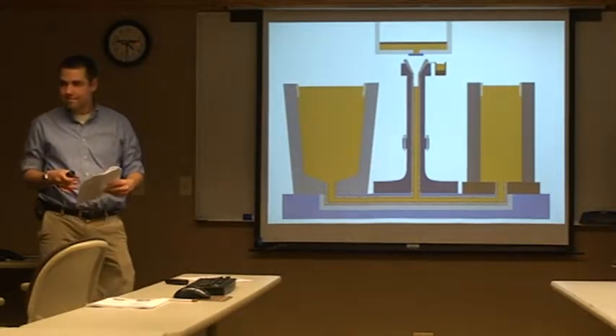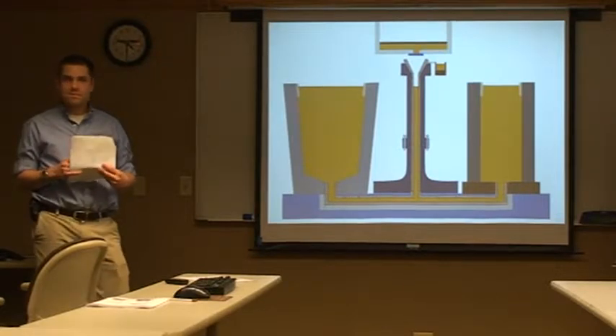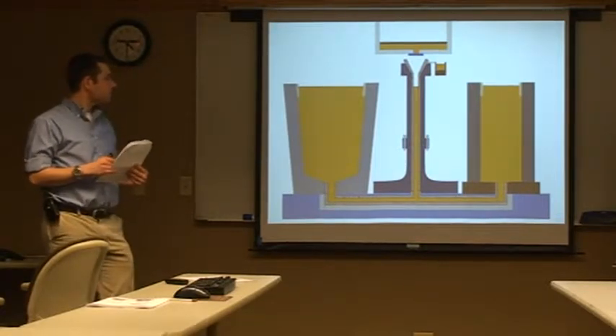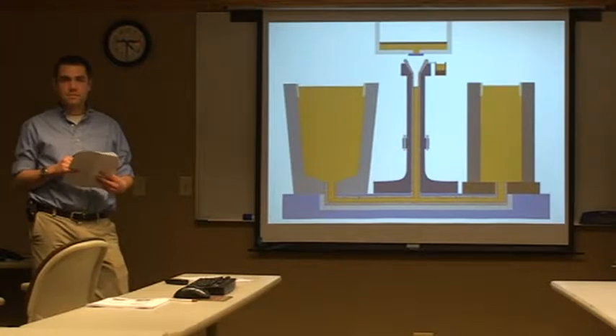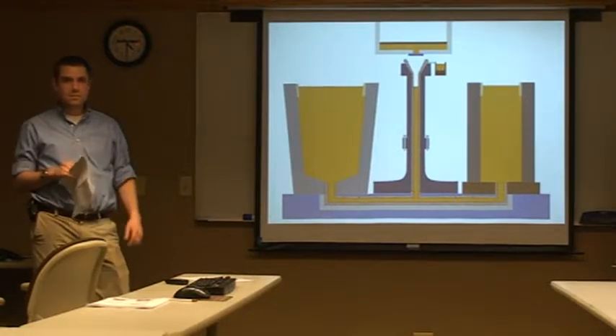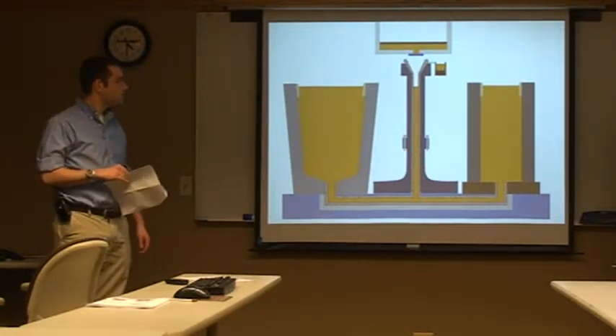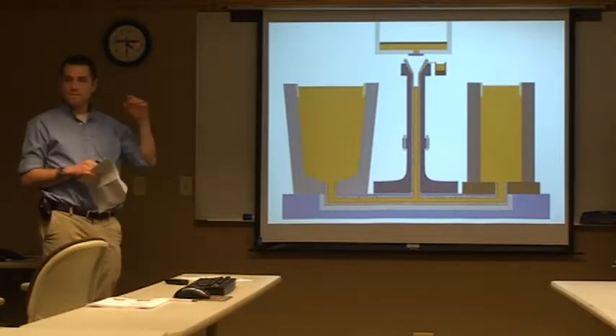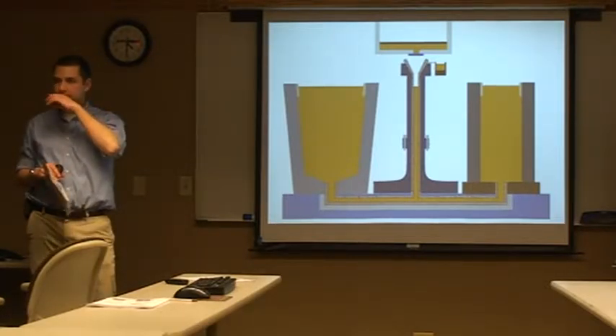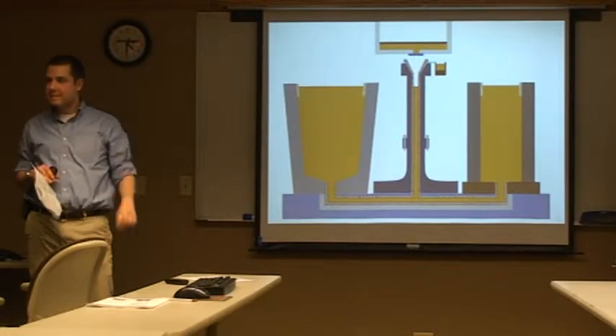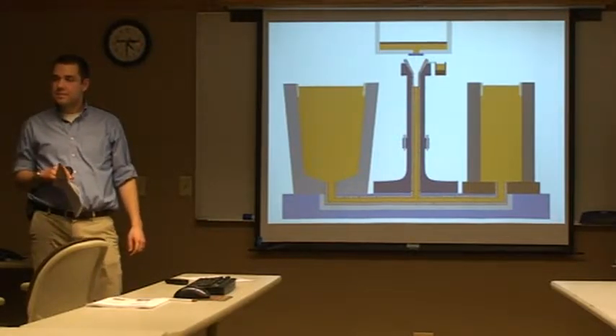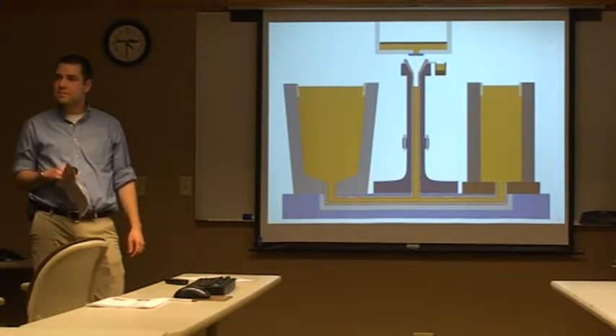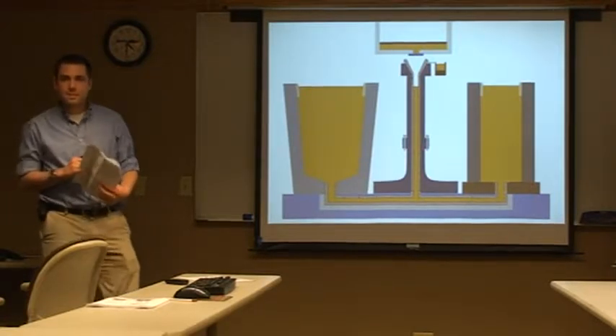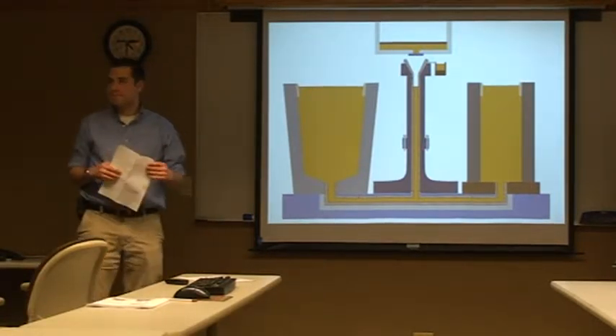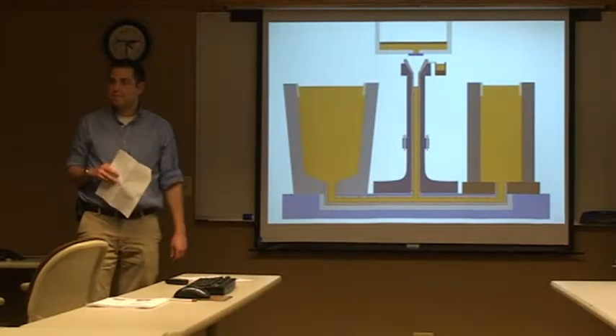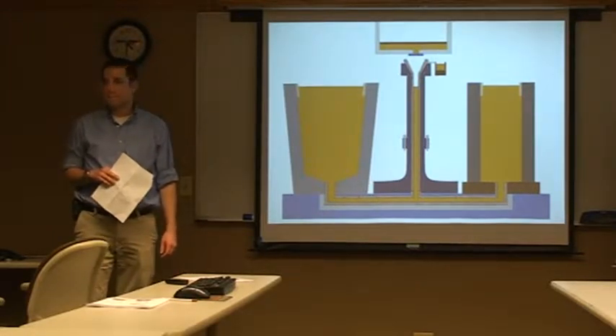The funnel part that you're looking at, the taper, that's not filled with steel, because the steel will only fill as high as the mold, and that trumpet part is always going to be higher than the liquid steel. The other thing is, the trumpet itself is cast iron, and it has a hole in the middle. The hole is much bigger than the trumpet brick. The hole might be 8 inches, 7 inches, I'm not sure. The trumpet brick has a diameter of 4 inches. So there's about a 1 to 2 inch gap all around that.